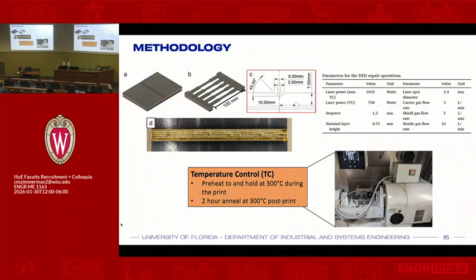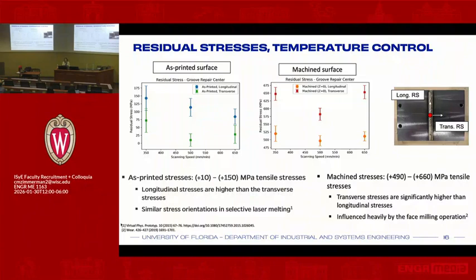And so some of the aspects that you're going to be seeing here is that in terms of stresses, you actually get pretty good tensile stresses. And when I say pretty good, it's because they're in the lower area of tensile stresses. They're not compressive. That will be the holy grail there too. But when you look at machining stresses, they are going to be significantly higher.